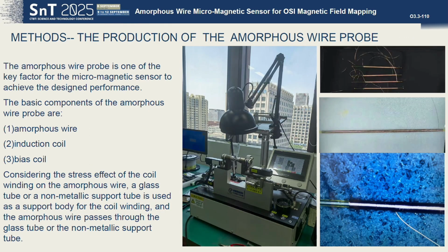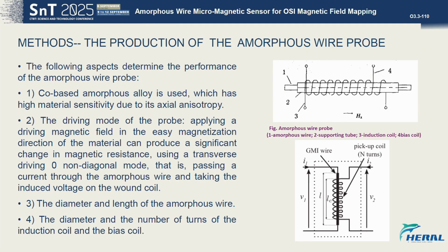The amorphous wire probe is one of the key factors for the micromagnetic sensor to achieve the designed performance. The basic components of the amorphous wire probe are amorphous wire, induction coil, and bias coil. The following aspects determine the performance of the amorphous wire probe. First, Co-based amorphous alloy is used, which has high material sensitivity due to its axial anisotropy. Second, the driving mode of the probe. The third is the diameter and the length of the amorphous wire. The fourth is the diameter and number of turns of the induction coil and the bias coil.